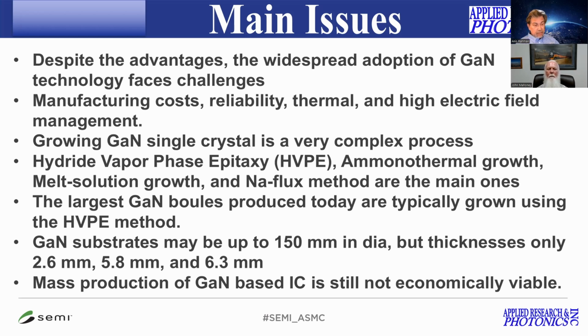Up until now, although they have been able to grow a 150 millimeter diameter boule, the thickness is still limited. The thicknesses reported in the literature are 2.6 millimeter, 5.8 millimeter, and 6.3 millimeter. In the 6.3 millimeter boule, the very top and very bottom are probably not useful, so from the middle you can get only a few wafers per boule. So far, gallium nitride technology is still dependent on silicon wafers by the epitaxy technique. That's one of the things the industry is trying to get over.